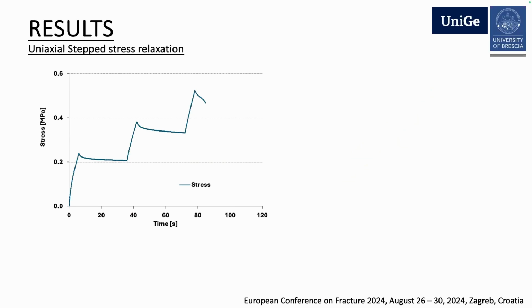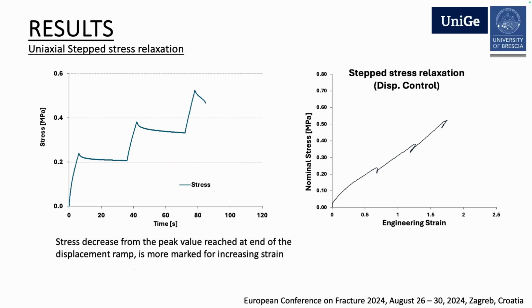Now, considering step stress relaxation, here the goal is to check whether the relaxation response is dependent on the applied strain level. And in this case, we have one specimen that is tested with increasing applied strain, and then it is relaxed. So what we observed is that actually the relaxation response seems to depend on the applied strain. So from a modeling point of view, that's an indication that we have to consider a viscous response, taking into account a non-linear viscous response.